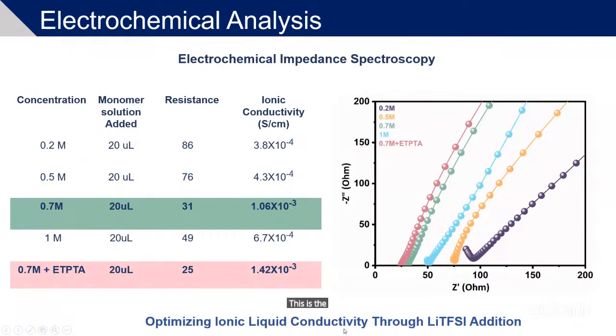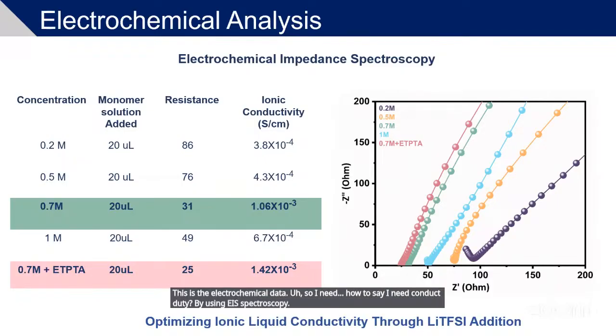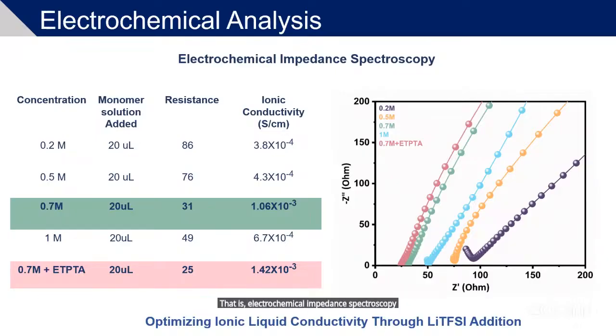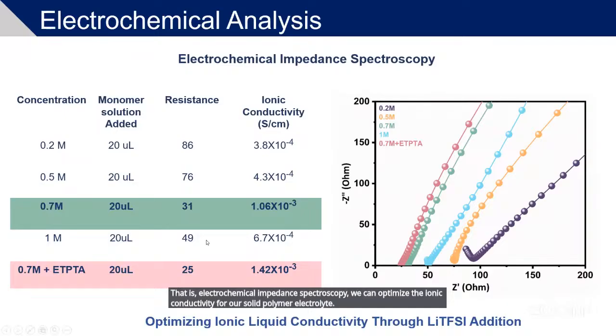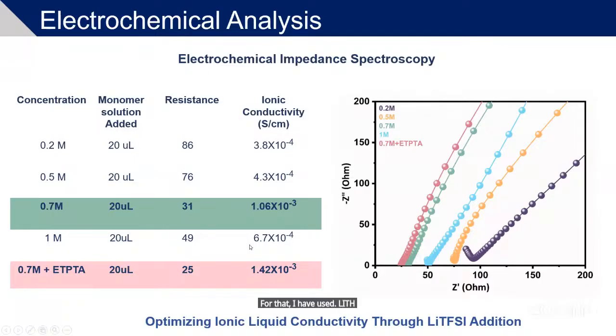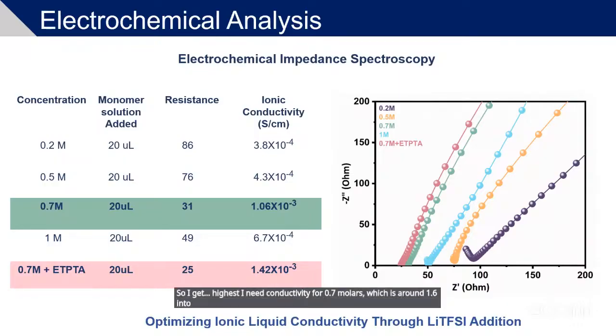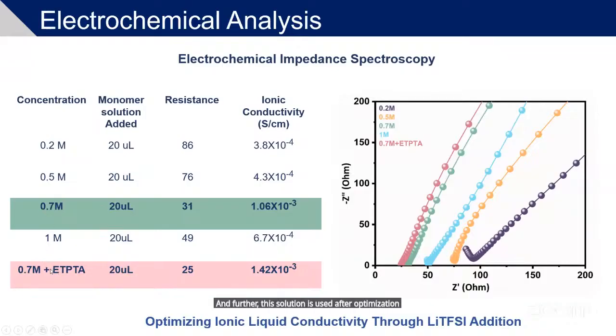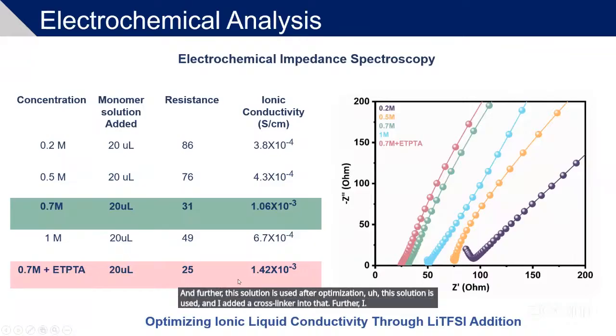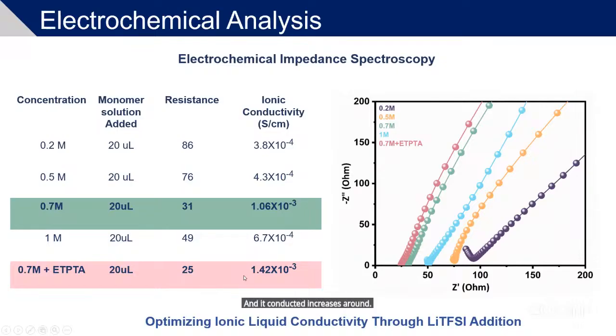This is the electrochemical data. How to check ionic conductivity? By using EIS spectroscopy, that is electrochemical impedance spectroscopy, we can optimize the ionic conductivity for our solid polymer electrolyte. For that, I have used LiTFSI as a salt and varied the concentration of LiTFSI from 0.2 molar to 0.7 molar. I get the highest ionic conductivity for 0.7 molar, which is around 1.06 into 10 raised to minus 3 Siemens per centimeter. Further, this solution is used after optimization, and I added a cross-linker into that. Further, ionic conductivity changes to around 1.42 into 10 raised to minus 3 Siemens per centimeter.